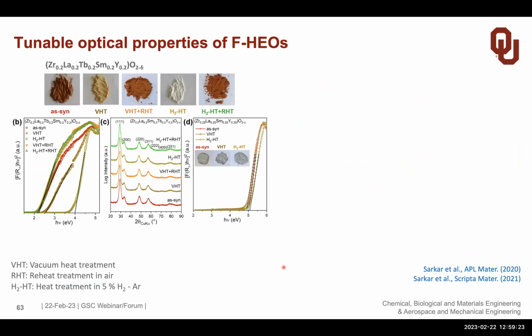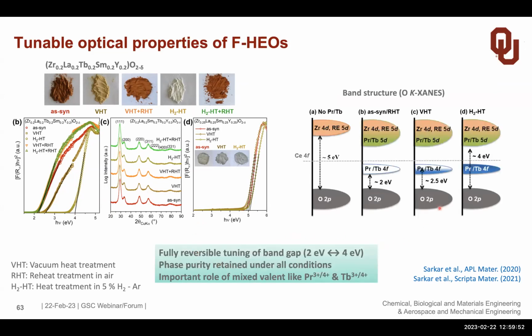We can also play around with the atmosphere that we expose the material to, and we can change the band gap. And substantially, we can change the band gap, which is measured over here, between 4 and 2.2 eV. We can do that reversibly by changing the atmosphere between hydrogen and air. And this, of course, is interesting. We could identify that this is due to intermediate band gap positions we can create by the different gaseous environment. So tunability of band gap can be an important and interesting aspect.